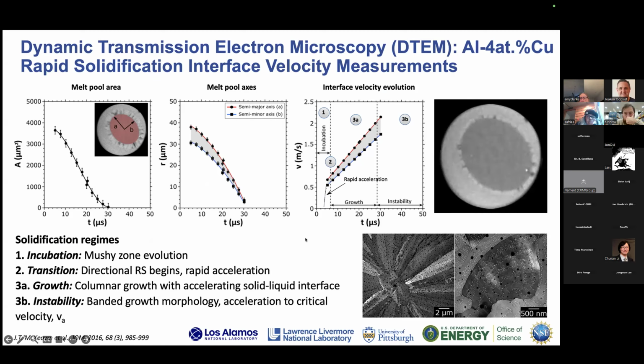And one of the neat things about this is that because you have a thin film sample geometry, you mitigate things like convection in the melt. So this makes it really nice to compare with solidification theory. And so this is an example of one of these spot melts in a DTEM movie. And then importantly, we can pull out quantitative information.